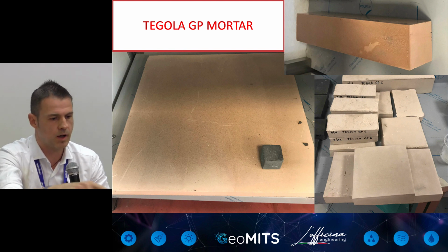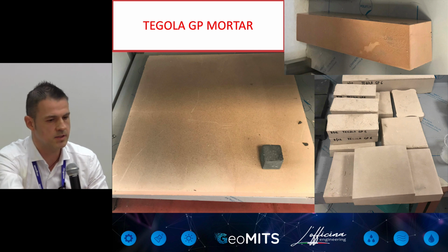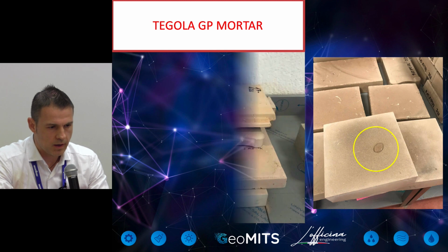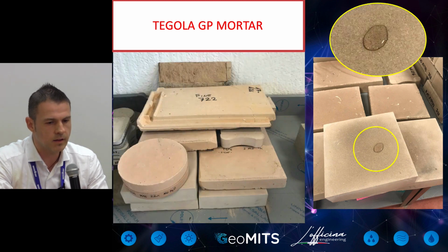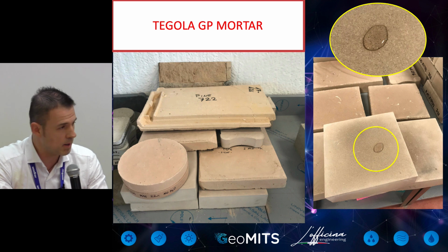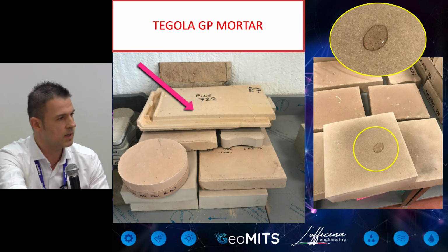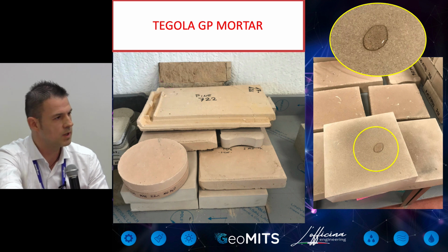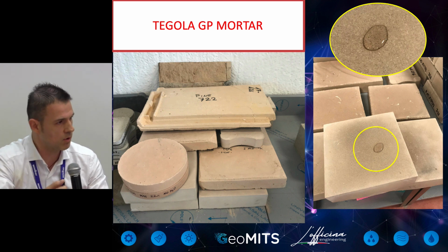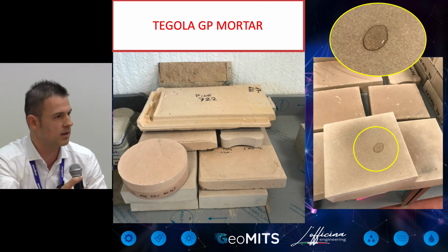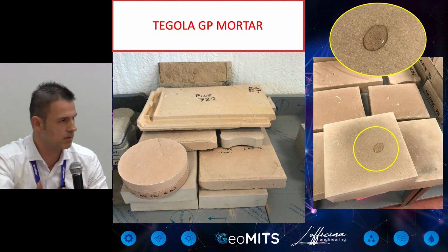And this, I realized also a big tile of 4 centimeters of thickness and 60 by 60. And of course, here I added a little additives to obtain immediately after hardening water repellency, because it's mandatory for this kind of application. And what you can see here is the roof tile that I tested. You can see the 722. This was the frost-defrost cycle when I removed it the first time, and it wasn't broken. So I put it back in the machine, and the machine stopped after 1,000 frost-defrost cycles, but the tile is still not broken. So I removed it and I kept it in the lab.